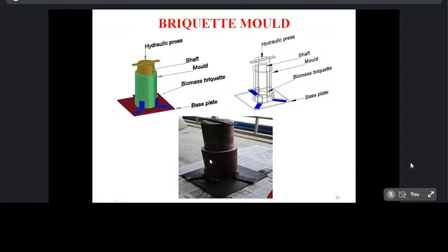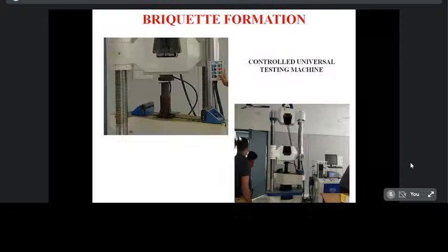The compaction piston was used, having a diameter of 76 mm, a height of 175 mm, and a total weight of 10 kg. The steel plate in the bottom portion was found attached to the edge of the base and is firmly tightened. The molded briquette was evacuated by expelling the plate from the base edge. The hydraulic press was used for production of the biomass briquette for getting the uniform size of the solid biomass briquette. This is the machine we have in our structural engineering laboratory in our Kongu Engineering College.